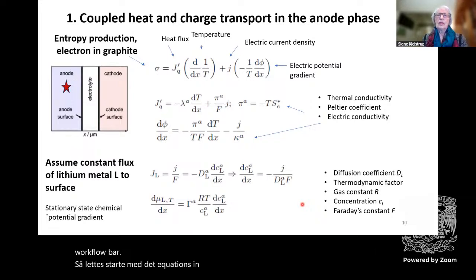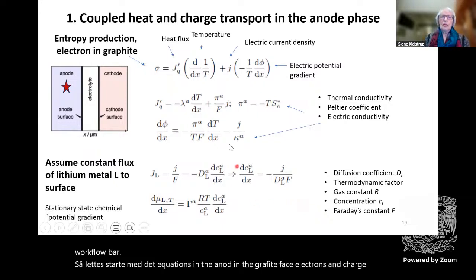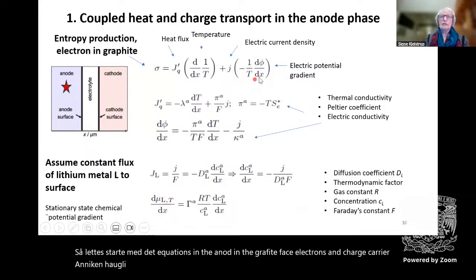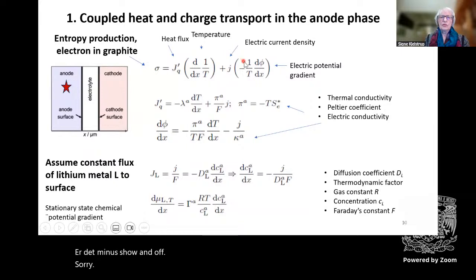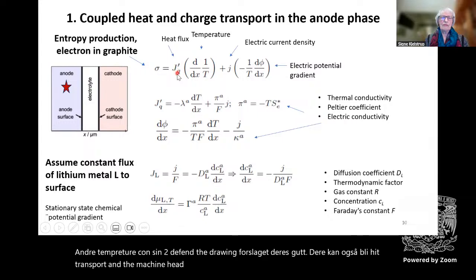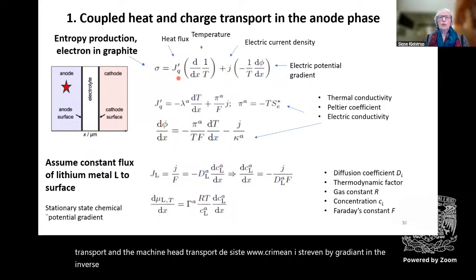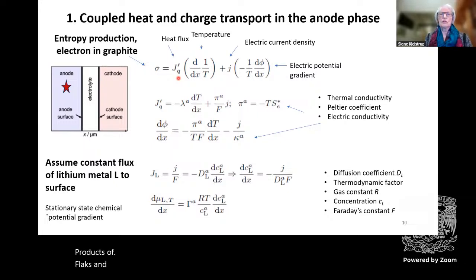In the anode, in the graphite phase, electrons are the charge carrier, and we can have electric current driven by the gradient in the electric potential, and the temperature comes in to define the driving force like this. But there can also be heat transport, and the measurable heat transport, this is why we have a prime here, is driven by the gradient in the inverse temperature. Two products of flux and force, that's the prescription of Onsager.